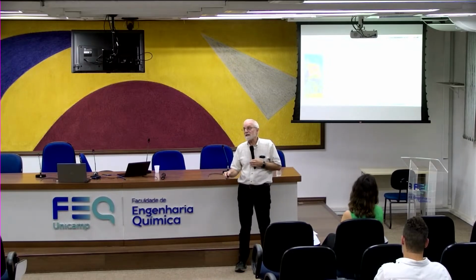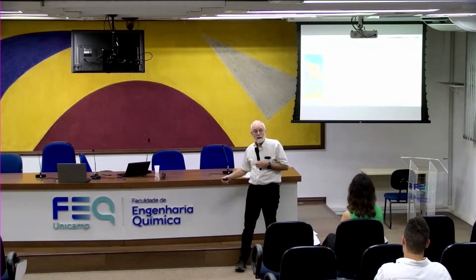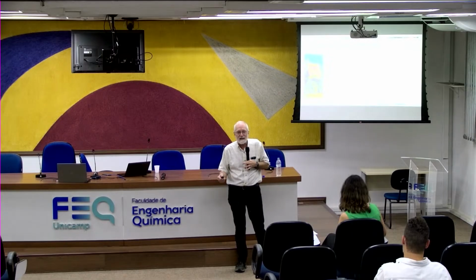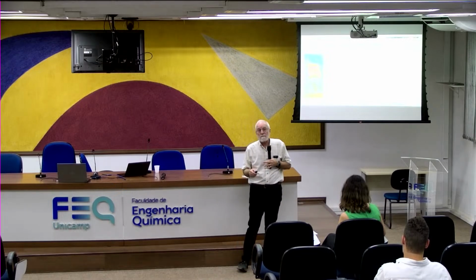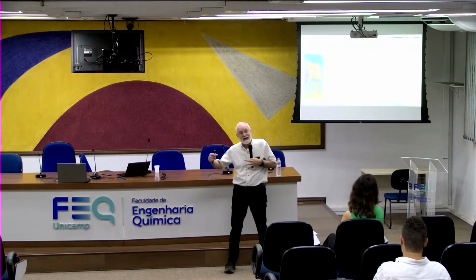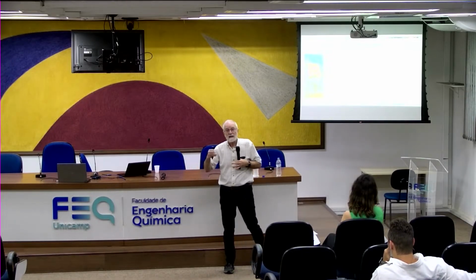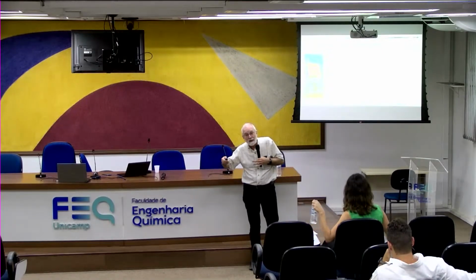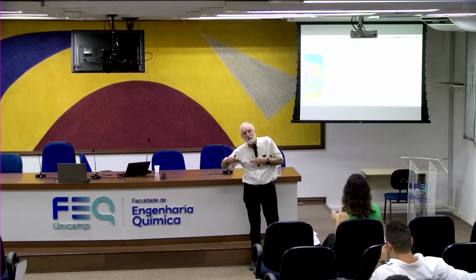And so the idea was that we look at lignin. So lignin is the brown material in wood. It's a very unusual polymer because it's cross-linked, it's a network, it's ill-defined. Nature usually makes well-defined. This one is a mess. It's highly aromatic, many phenolic groups, and the way that it is assembled inside the plant is that various phenols in the presence of an enzyme like laccase control the coupling of two phenolic groups. So you make a new carbon-carbon bond by phenolic oxidation.